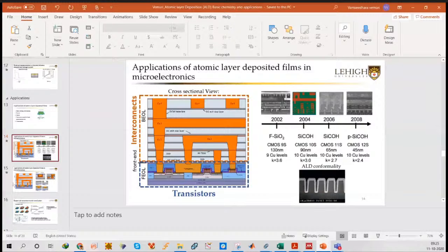When you have a silicon substrate with hydroxyl termination, it could not be hydroxyls everywhere because no matter how much you functionalize, there is some water adsorbed onto the surface. Sometimes there is adventitious carbon, which would be blocking the active sites. No matter how much you clean and put it in the reactor, there is some time lag. And that time lag is enough to give some adventitious carbon and water adsorption. So it blocks the active site. So it won't be a monolayer in the first layer that you put. But if you put 2 or 3 cycles, it will be covered completely. That's why. Oh, okay. It is good.